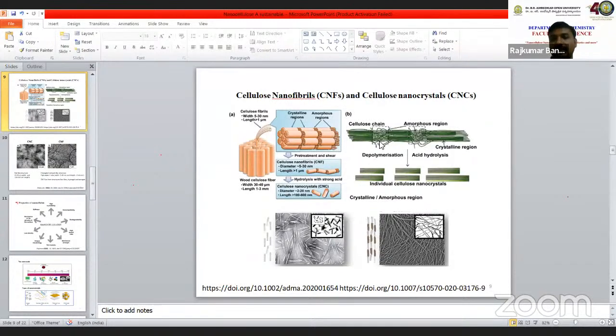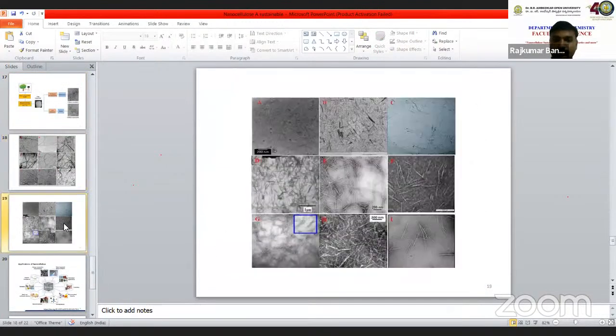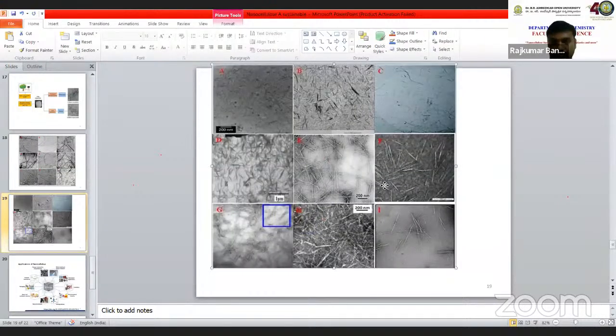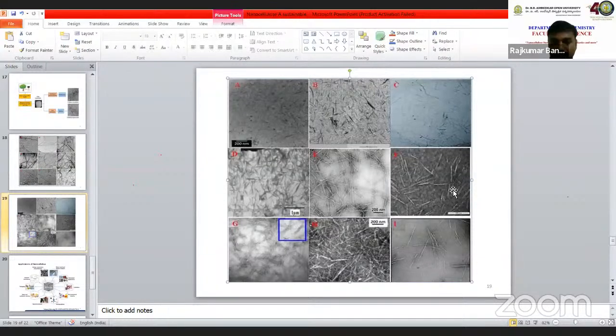Compared to the crystalline part, the amorphous part is a little weak and easy to digest. Because of the strong acid, the amorphous part will dissolve in the acid, and the crystalline part will remain. Then we separate them using dialysis and other techniques, and you get this kind of nanocrystals. These are representative images of cellulose nanocrystals. This is a thin, rod-like structure, and they are highly crystalline in nature. Due to their high crystallinity, they are very strong and can be used as reinforcement for other plastic materials, improving the mechanical properties and tensile strength of those plastics.